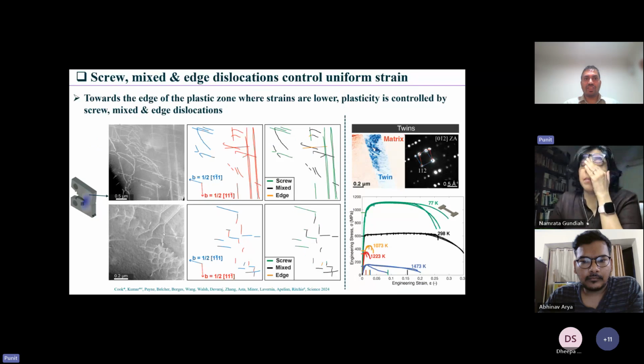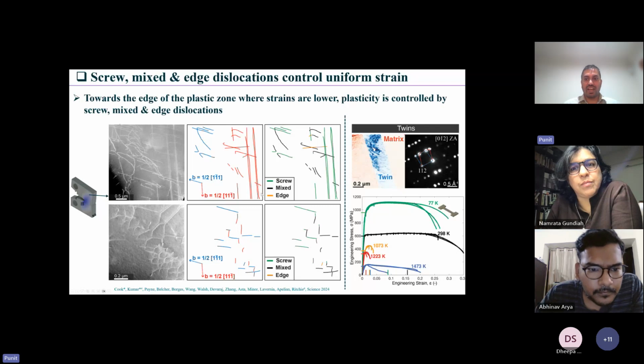So what we think from our theory is that if you look at the dislocation activity, in the region where we see uniform strain, the strain hardening is driven by this dislocation activity. And once you reach these regions, you start nucleating the kink band. Now your material starts necking, and this region is driven by kink band formation. That's what we believe: uniform strain is driven by dislocation interaction, but necking is driven by kink bands during tensile deformation.